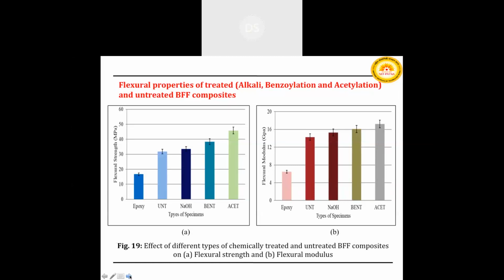Next, the flexural properties of treated alkaline, benzylation and acetylation and untreated Borassus fruit fiber composite. This analysis shows that the fiber treatment has a significant effect on the flexural properties of the composite. The flexural strength and the modulus obtained under the flexural loading are quite low for the untreated Borassus fruit fiber composite as compared to the treated Borassus fruit fiber composite. Whereas the benzylation treated composite shows more strength and more modulus as compared to the alkaline treated composite.